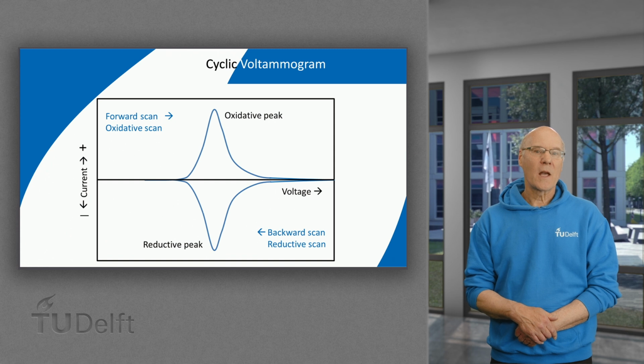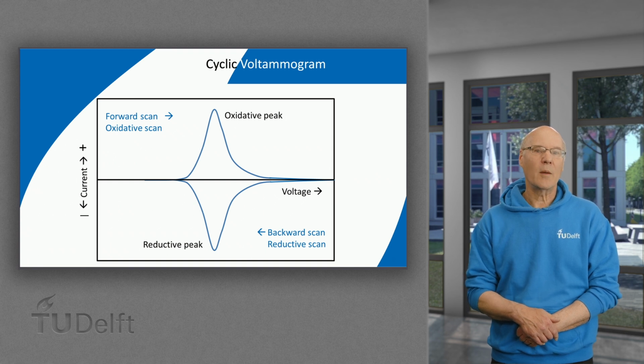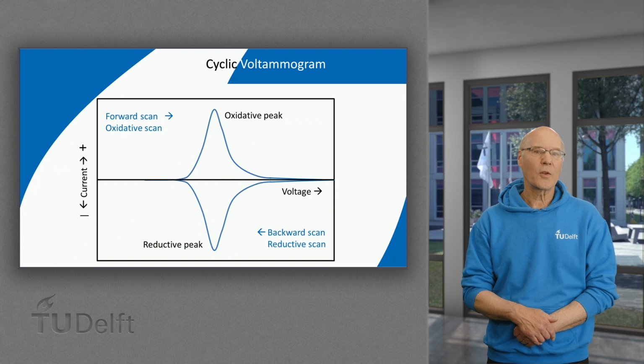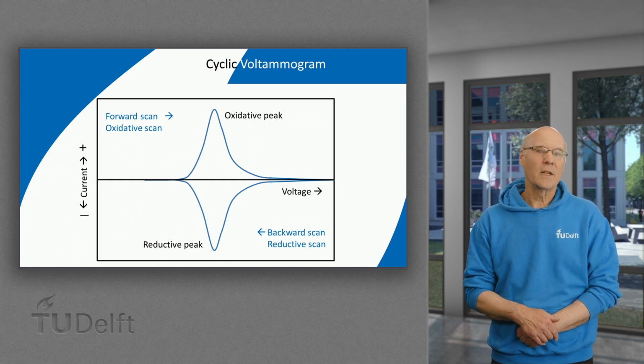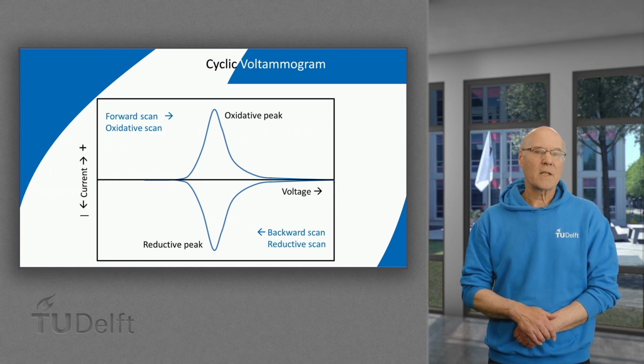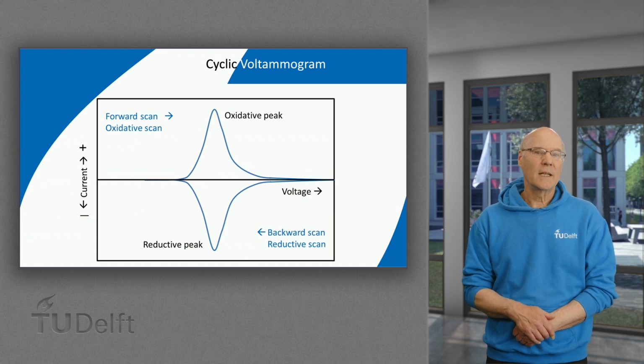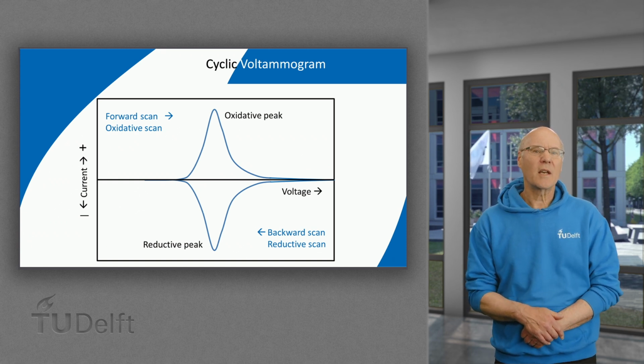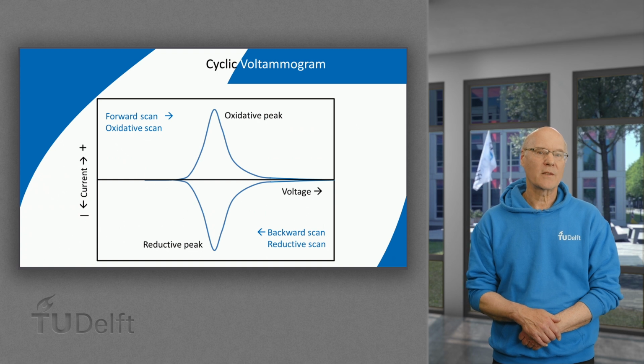In more detail, cyclic voltammetry involves applying an increasing potential, swept linearly with respect to time, from an initial value to a final value and then back to the initial value. The response of the electrochemical system is then a plot of the resultant current against the applied potential to produce this voltammogram. A plot displays the current versus potential and provides detailed information about the oxidation and reduction process.